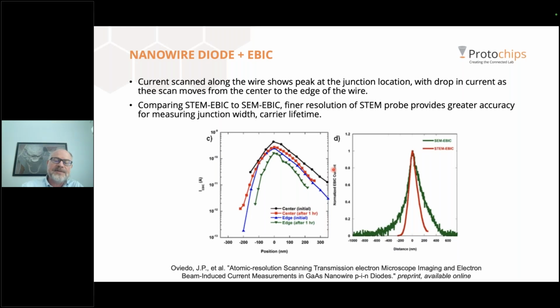Next, there's data from the center of the nanowire versus the edge of the nanowire. So think of the wire as a cylinder. In the center, the STEM beam is interacting with more volume. As you get close to the edge, it interacts with less volume, so it creates less current. You can also see less current with time. The authors measured it initially and then after an hour. After an hour, the current from both the center and edge goes down, so they can attribute that to the formation of a passivation layer, which would impact its characteristics. And you see a greater extent of that at the edge where the passivation layer would be more impactful.